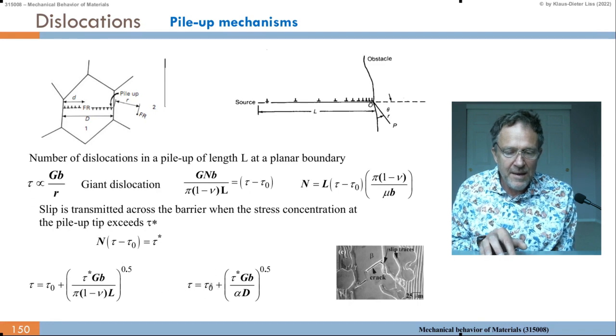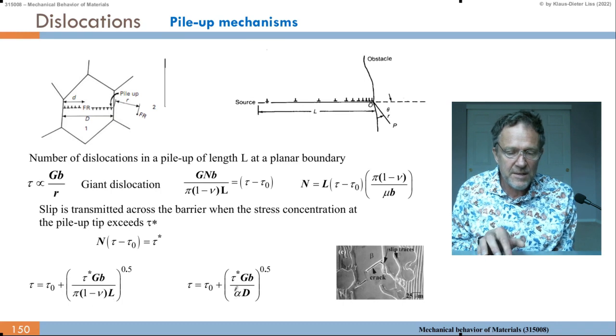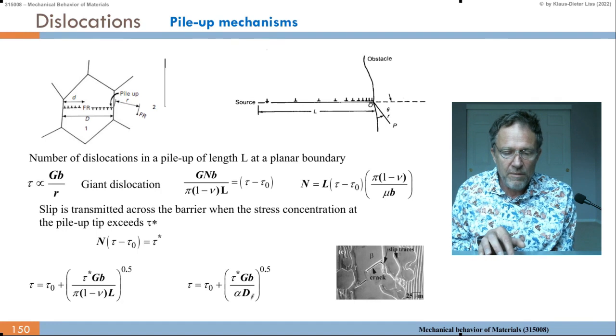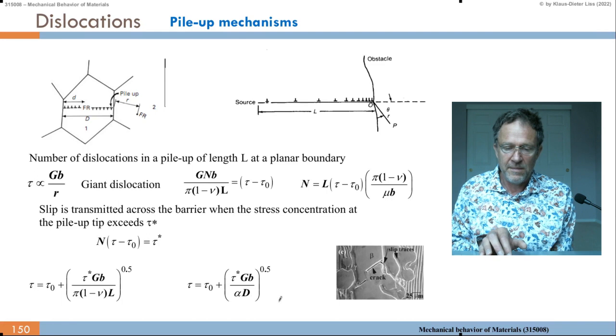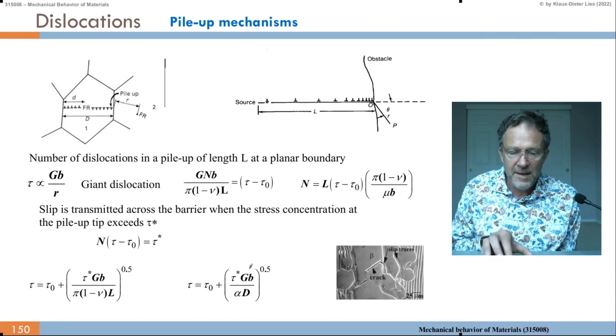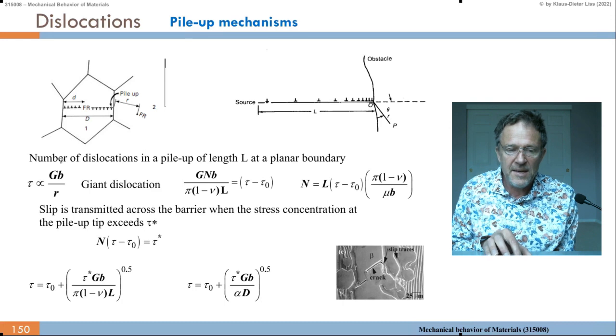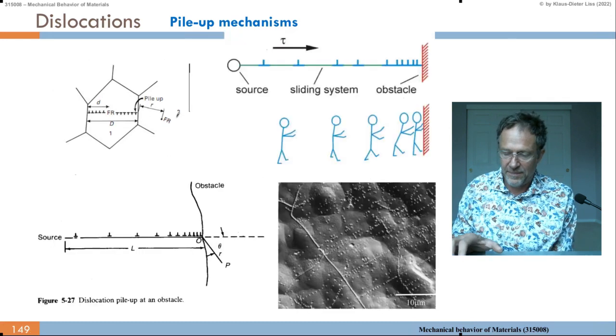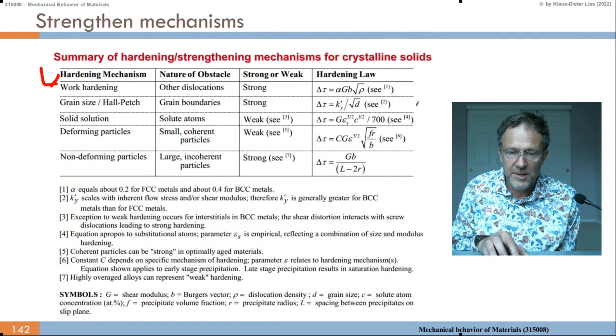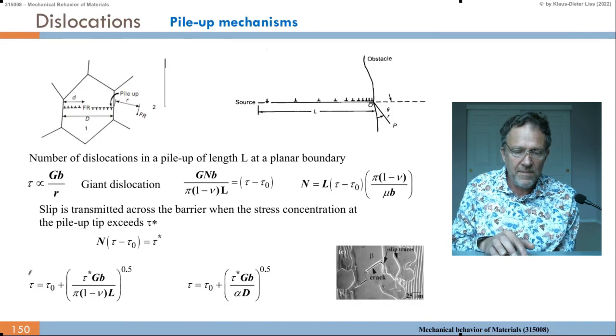So tau becomes tau 0 plus, and now we put everything into a constant alpha, times the diameter. The L is proportional to the diameter, and all the other constants we also put into the alpha. So the square root of tau star Gb over alpha D. And this is Hall-Petch strengthening, where the shear stress goes proportional to the square root of 1 over the grain size D, grain diameter D. So delta tau equals k prime over square root of D. We put everything else into k prime, basically those constants.